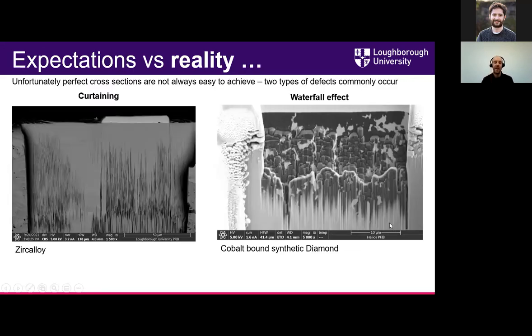But what actually happens in some materials is that we get a lot of defects when we're cutting. One of the main defects that we see is curtaining, where we get ripples running down the surface of the material. This is something that we see a lot more with xenon ion beam systems than we do with gallium systems, and it's something that we've had to try and overcome. And for materials like diamond, graphite, silicon carbide, and aluminium nitride, we've seen things like waterfall effects, where you get this like Giant's Causeway forming on the front of your sample. Like these sort of steps.